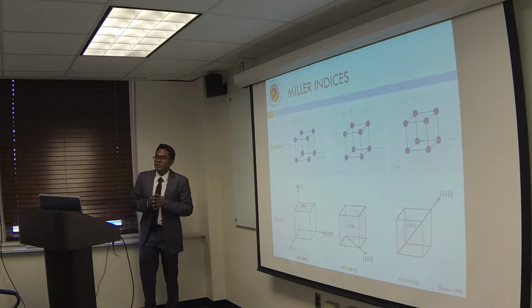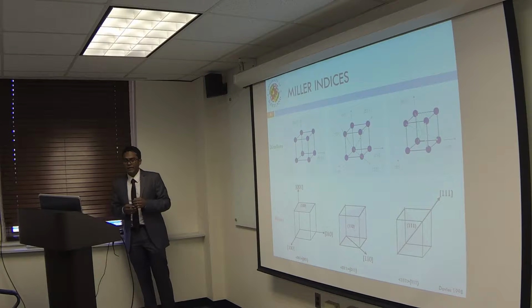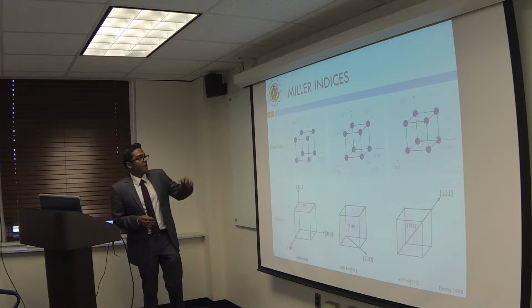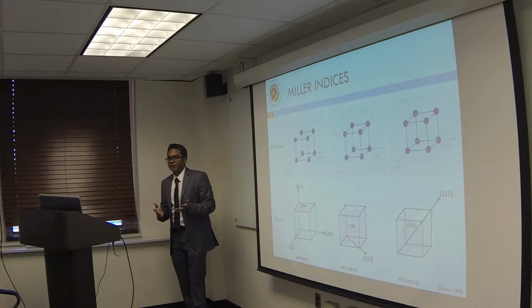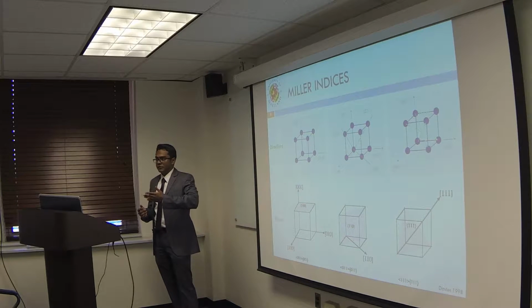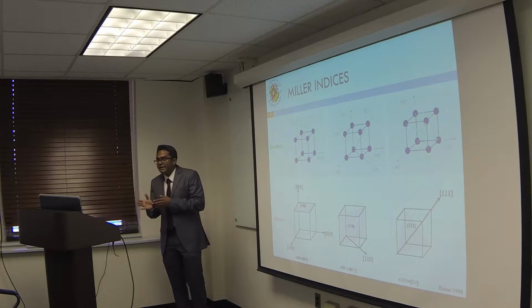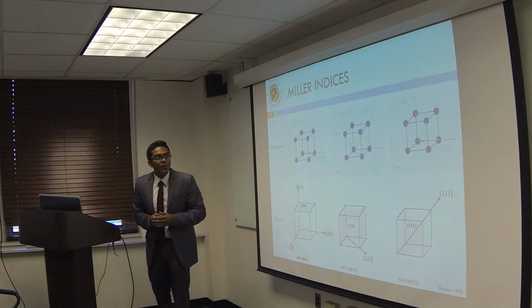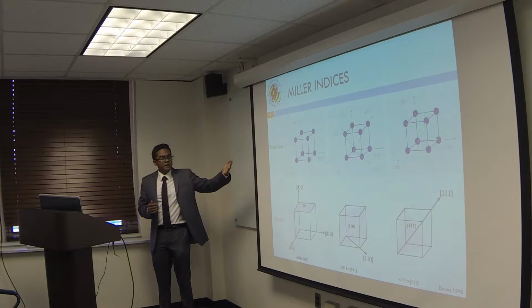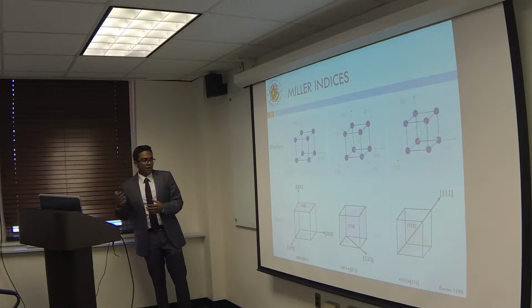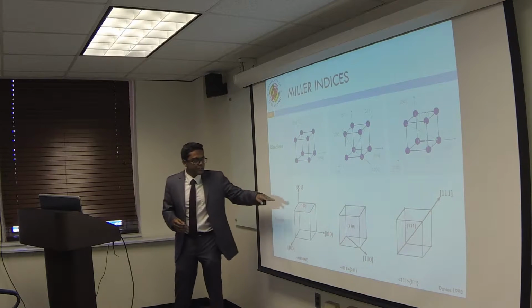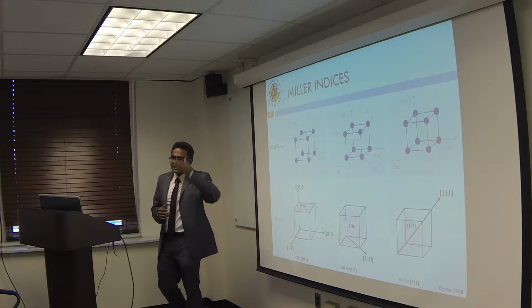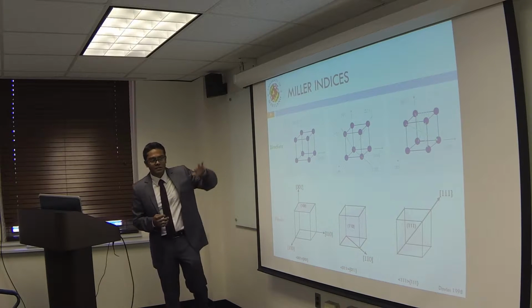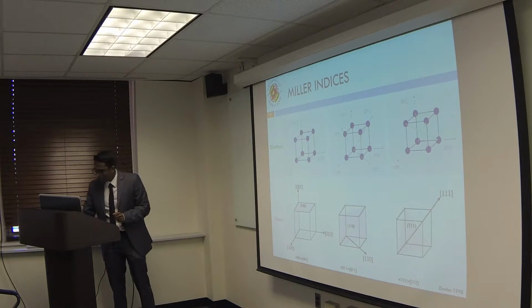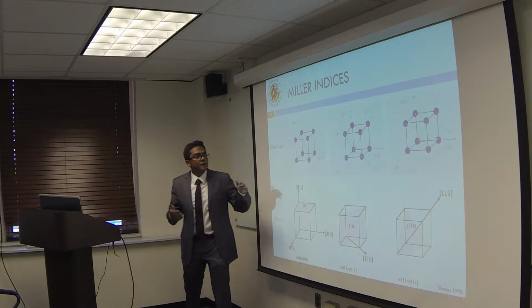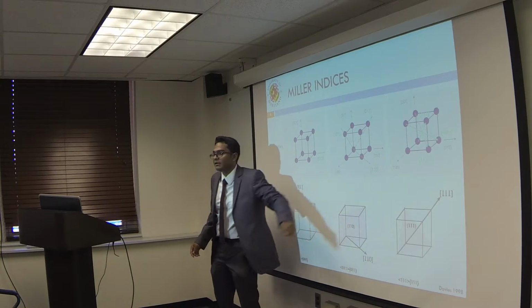I'm going to give you a brief introduction into Miller indices, which is used by material scientists to define the different crystallographic directions in materials. So when it comes to cubic materials, there are 3 primary crystallographic directions. These are the 100 directions, which are along the edges of the cube. The 110 direction, which is the face diagonal of the cube, the 6 face diagonals of the cube. And the 111 directions, which are the body diagonals of the cube. And these primary directions have a primary plane associated with each of them. So the 100 directions are the faces of the cube. The 110 direction is a slice made along the face diagonal of the cube, and the 111 direction is a slice made along the body diagonal of the cube. So with this in mind, it's important to note that the negative Poisson's ratio is observed along the face diagonal, or the 110 direction.